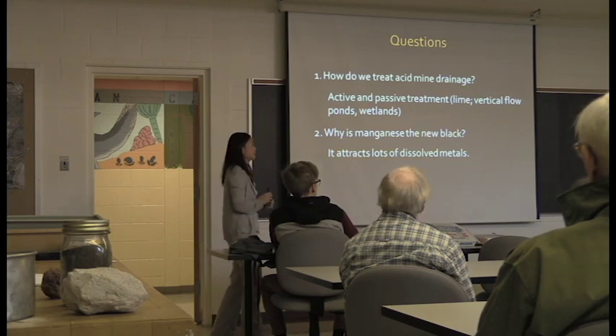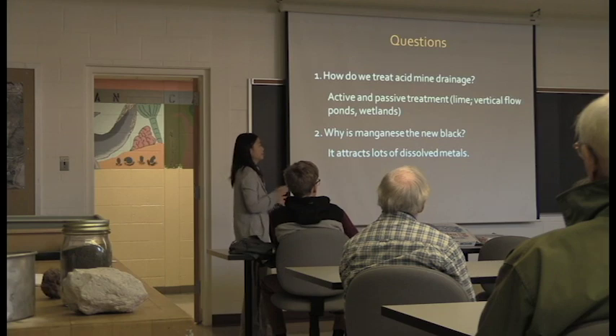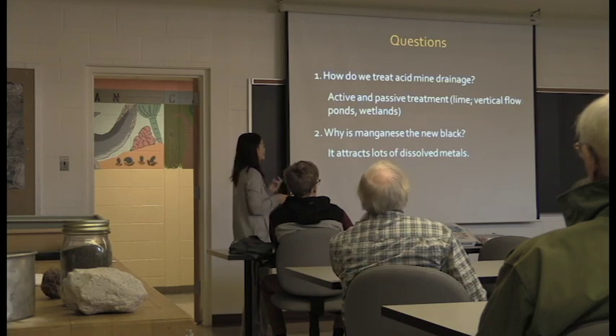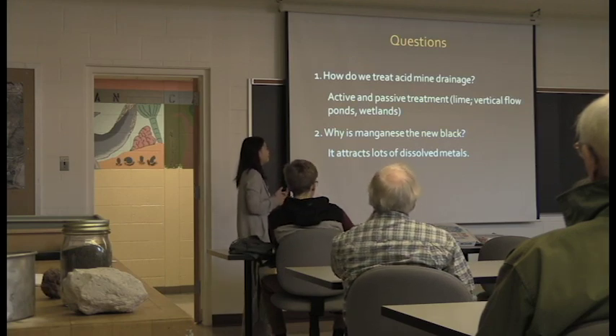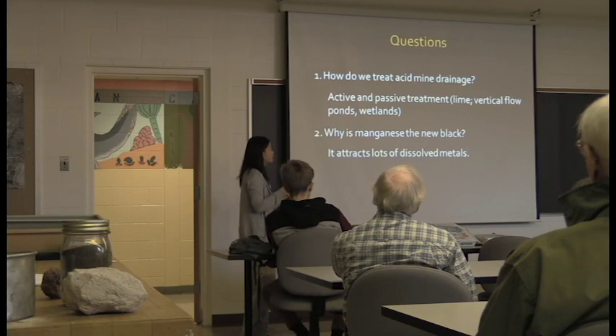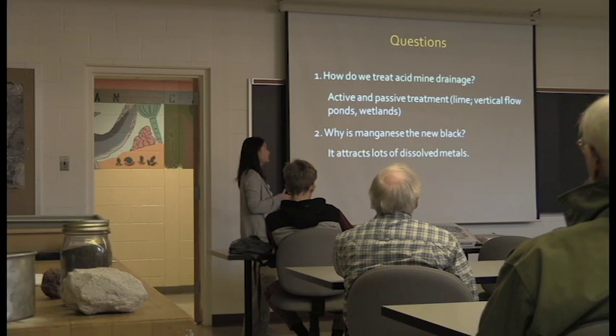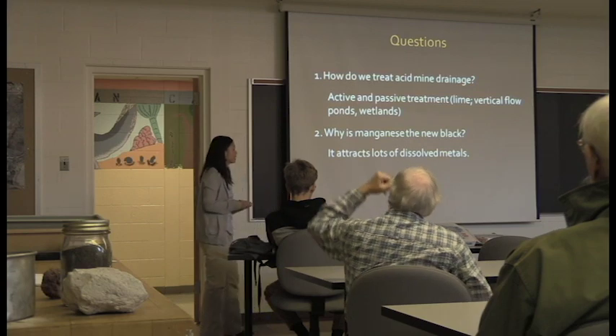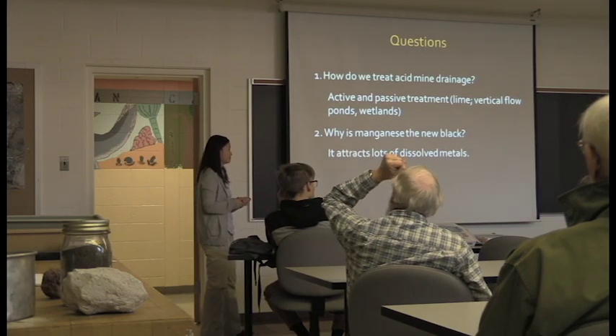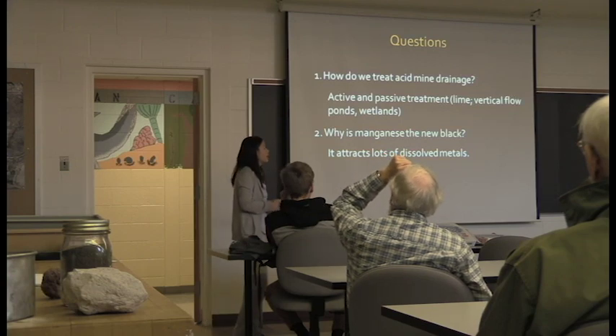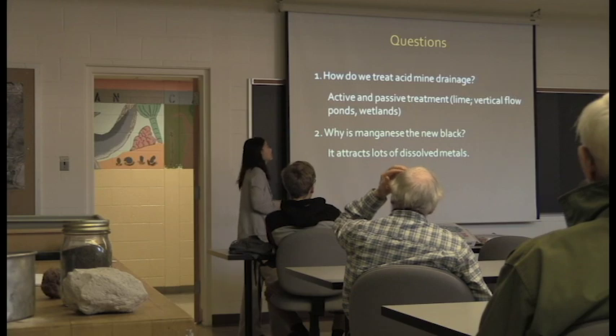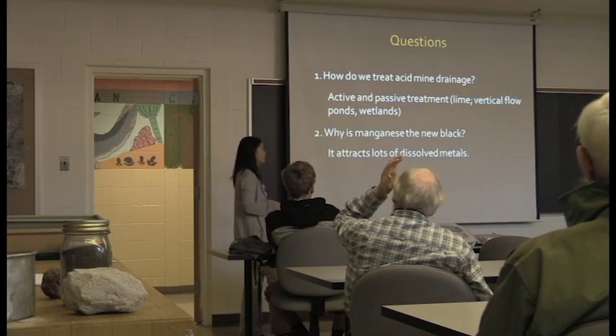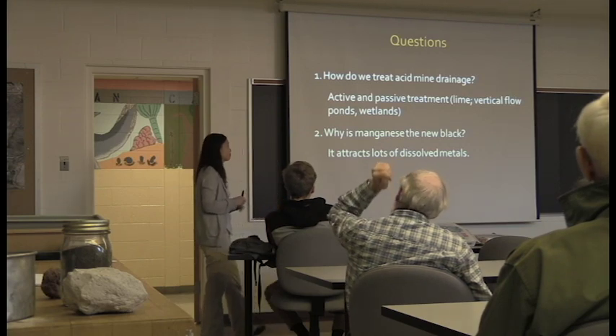Yeah, so you do see a significant decrease before and after the birnessite. And so the sites that we have, they regularly monitor these to see what they need to adjust for the site. And so they do see decreases over time. So that's evidence of the manganese oxide taking up these other metals. Yes. So it's evidence that manganese oxides are able to take these things up.